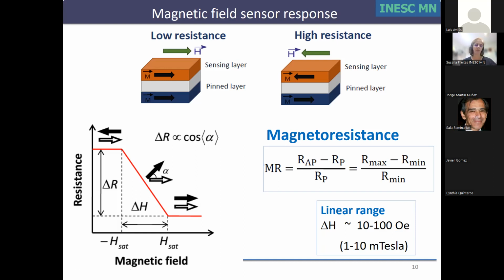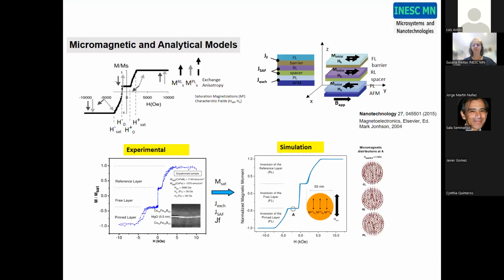And what is the core knowledge that we should have here? We should always maximize the minimum and the maximum amplitude for the resistance. So this variation should be as large as possible. And this is actually the magnetoresistance, so it's the variation in resistance normalized by one of the resistance levels. And of course, this requires a good knowledge of magnetism. There are several layers here. We have not only one magnetic layer, but we have 3 or 4 or more magnetic thin film layers that are integrated in the magnetoresistive stack.